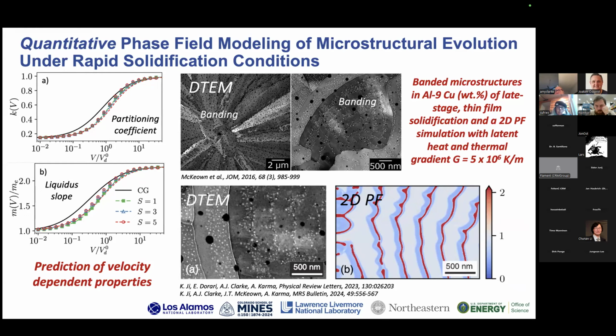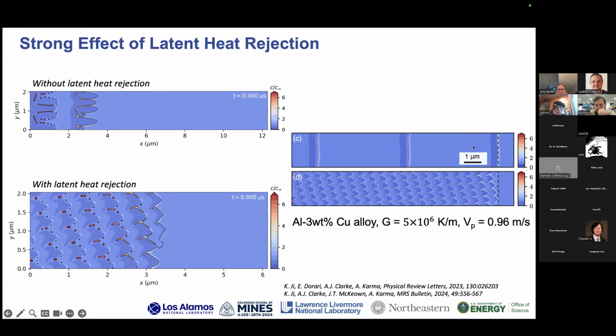So this is an aluminum copper example, again, where we see banding in the central region of the melt pool. And here is a 2D phase field simulation from this new implementation of their model. And we can see that they do indeed predict the banding. And one of the important things about this model is that it includes latent heat. And these are some nice simulation results. Hopefully these movies play, from my colleague Alain Karma's group.